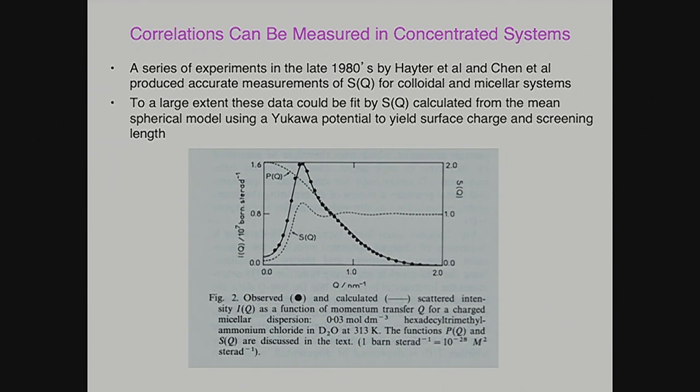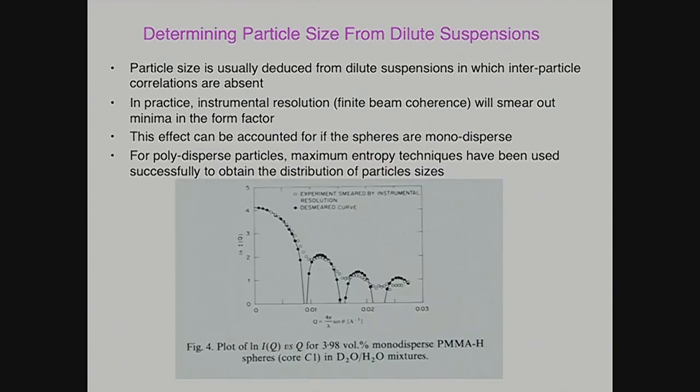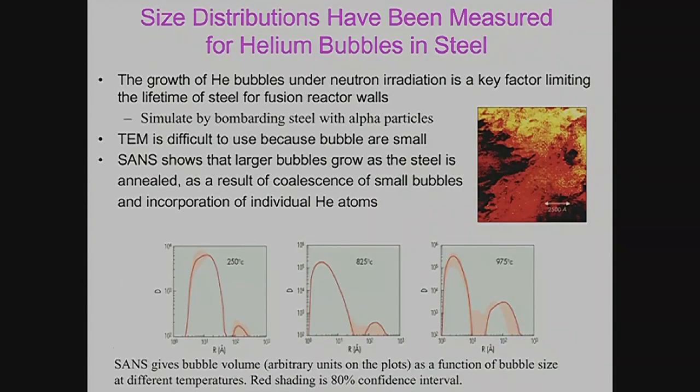So in small angle scattering, you can measure things very similar to what you would measure in a monatomic fluid, but over different length scales. So the S of Q for argon was measured at much higher Q, much smaller length scales. It's the size of an argon atom. And this is measured at much smaller Q because it's for latex particles, same stuff as you have in water-based paint, right, that have a size of, I don't know, a few tens of nanometers, rather than sub angstrom. So that's that. I don't want to go through that.